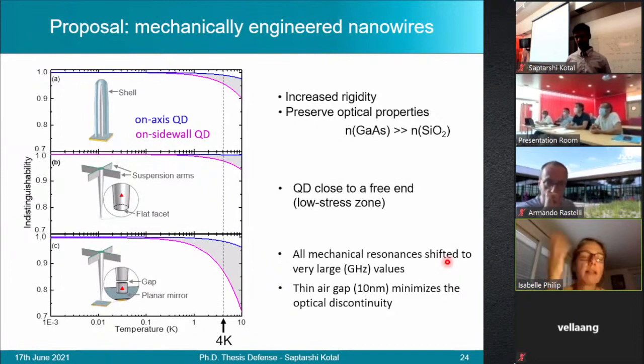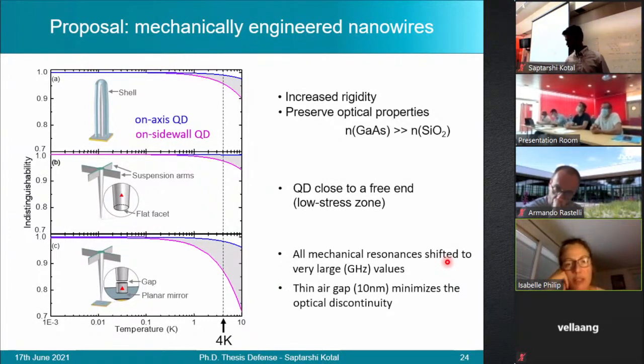And in that case, as you mentioned, the flexural mode has shifted to very high frequency, something like 2 gigahertz. So why do you lose so much in terms of indistinguishability when you go to relatively high temperature compared to the two other geometries? I don't really understand why you have this decrease in indistinguishability there.